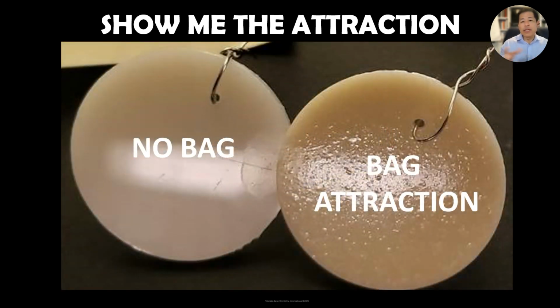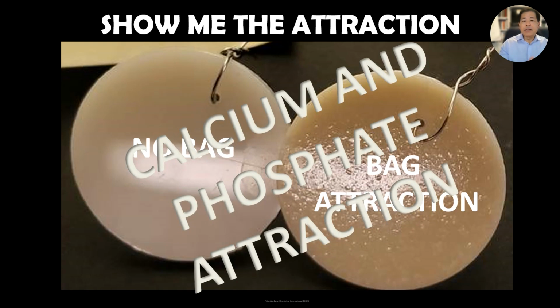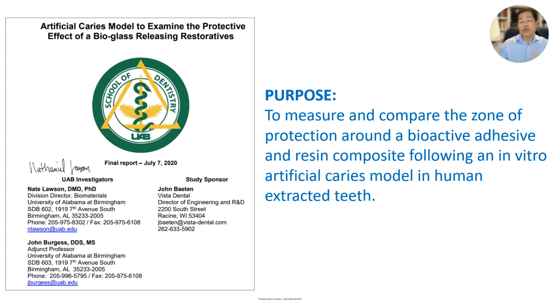At the end of 2 weeks, you take those out, you rinse them off, and the disc on the left-hand side, which has no bioactive glass in it, you can see it's just clean composite. On the right-hand side, it has this orange peel effect because the calcium and phosphates were attracted to that material, and so it has that little texture. Now, that's not a bad thing, but that is just proof that we can attract calcium and phosphates to our composite or a restorative material when we have the Bioglass 45S5. Now, you take these two properties together, and that's kind of what this study by Dr.